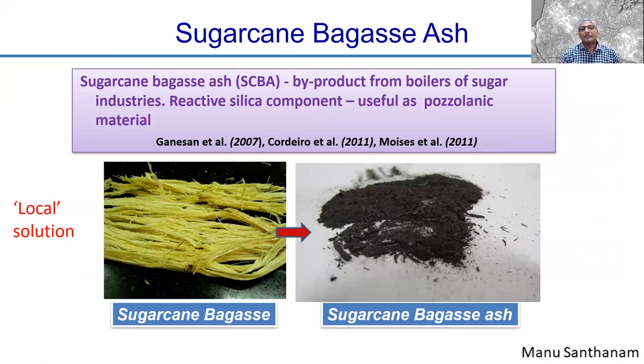Okay, now let's change gears and move to a local solution, right? So here we're talking about bagasse ash. Bagasse is nothing but the crushed cane after extraction of the sugar. It gives you these fibers, which we call bagasse. And this bagasse has very nice calorific value. So it's usually burnt to obtain the advantage of utilizing the heat for other processes in the sugar mill. So in this case, it is burnt typically in sugar mills at about 550 degrees Celsius. The resultant ash is simply called sugarcane bagasse ash. And that's what it looks like. You can see that it looks like a fine-grained powder, but there are also these other fibrous-looking materials present inside the bagasse ash. The fibers are obviously coming from these fibers that are present already in the bagasse.